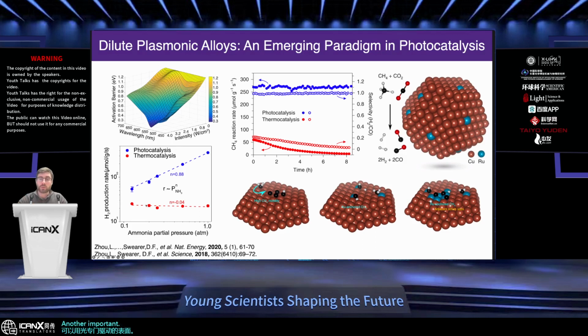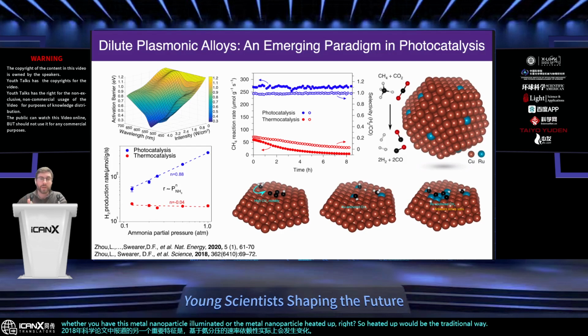Another important feature that was reported in the Science paper in 2018 was that the rate dependence based on the partial pressure of ammonia will actually change whether you have this metal nanoparticle illuminated or the metal nanoparticle heated up, right? So heated up would be the traditional way that the chemical industry has been operating these systems for 100 years. We see a 0th order dependence, which means it really doesn't matter how much ammonia is in your system. You basically have a rate that is constant.